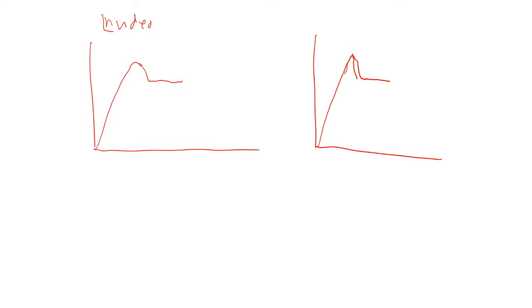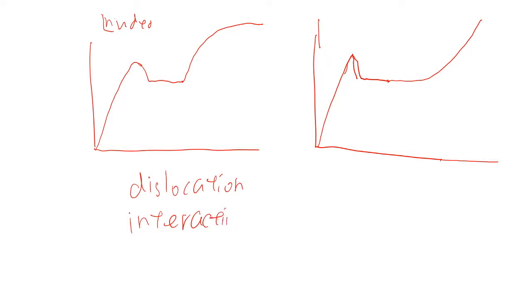the entire gauge length, which results in a large tensile stress. And strengthening also happens in the polymer after the plastic flow has propagated along the entire gauge length, which also results in a significant increase in the flow stress. But the difference is that the work hardening of the mild steels is due to dislocation interactions. But the strengthening of the polymer is due to the molecular